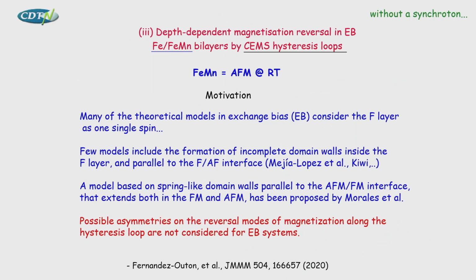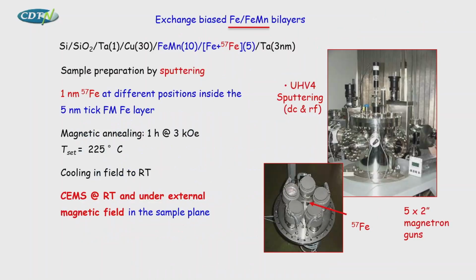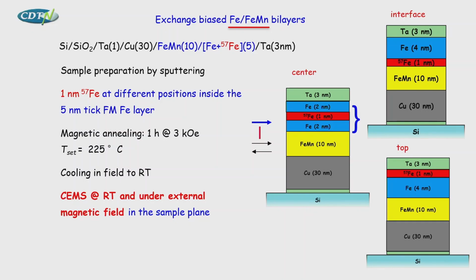Okay, but then we wanted to complete that kind of work without a synchrotron, okay? How could you do that, okay? And we tried to do it at home, doing standard CEMS, okay? Then we chose another antiferromagnet, iron manganese, that is ordered at room temperature, okay? That is what we did in our lab. Many of the theories on exchange bias consider the ferromagnet layer as a single big spin, okay? They do not consider asymmetry in the reversal of the magnetization, okay? And then what we did is that we used our sputtering system to grow samples with iron 57 at different positions. No?